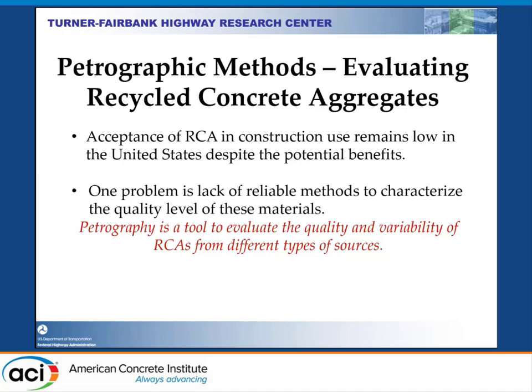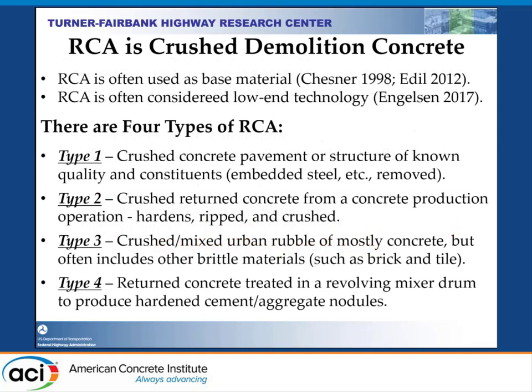What I'm talking about today is how we use the petrography method in evaluating recycled aggregates. Acceptance of RCA in construction use remains low in the U.S. despite the potential benefits. One problem is the lack of a reliable method to characterize the quality level of these materials. Petrography can be a good tool to evaluate the quality and variability of RCA, whether it's from a single source or different sources. A simple definition of RCA: it's crushed demolition concrete, often used as a base material, often considered a low-end technology.